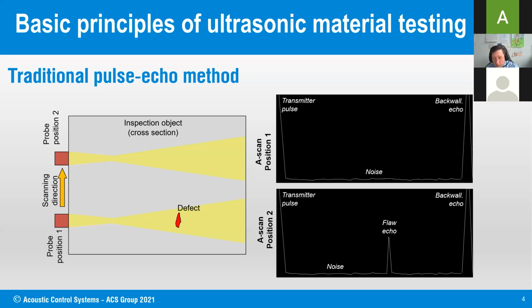That means a big defect gives a big or strong signal, small defects a smaller signal, and the estimation is based on sensitivity calibration. Before we go for the testing, we calibrate the instrument on reference specimens with artificial defects, and then we compare the reflectivity of the real defect with the reflectivity of the artificial defect, and give the values of the defect size in those artificial defect units. Might be flat bottom holes or side drill holes or notches or whatever.